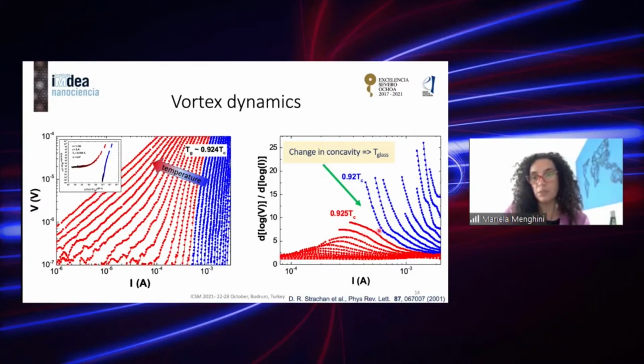And this change in the concavity of the curves has been associated previously with the liquid to glass-like phase transition. So that is also consistent when we do this scaling of the resistivity with temperature with proper parameters, and we see that the curves scale on the liquid phase altogether, while on the solid phase they're also overlapping. And then the transition temperature determined like this is similar to what we get from this analysis of the derivative of the IV curves.